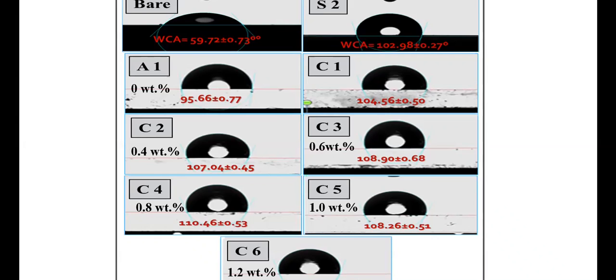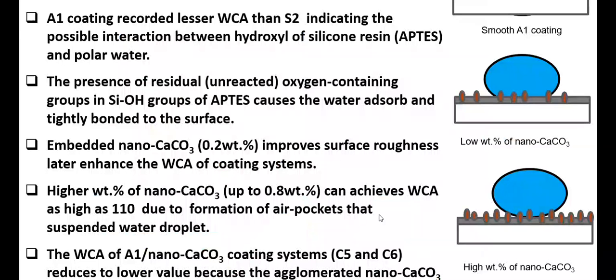The contact angle increases to 107, and with 0.6 weight percent, it increases to 108, and with 0.8 weight percent, it increased to 110. But after that, it shows a decrease, and this is due to the agglomeration of nano calcium carbonate on the surface. This is what happens when we put nano calcium carbonate particles on top of the resin.